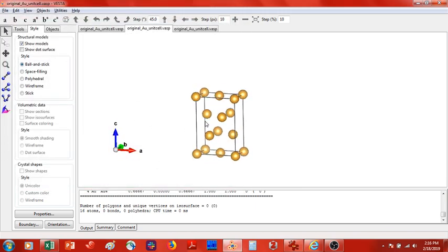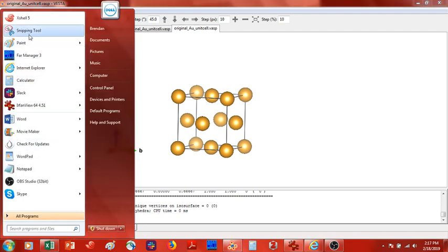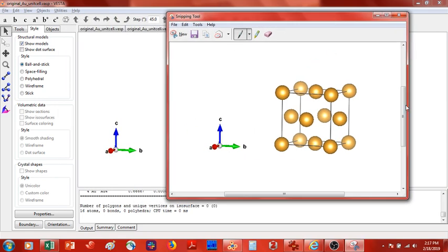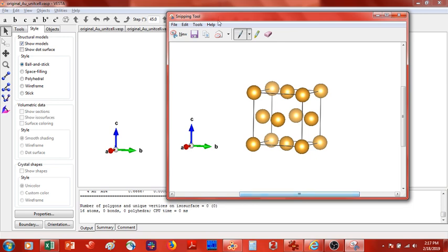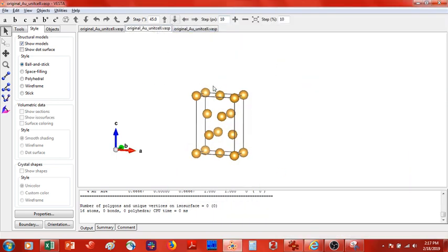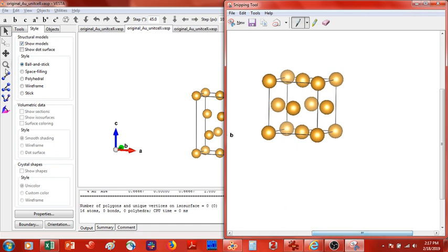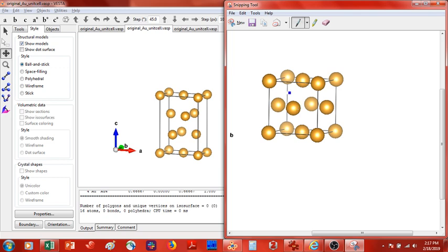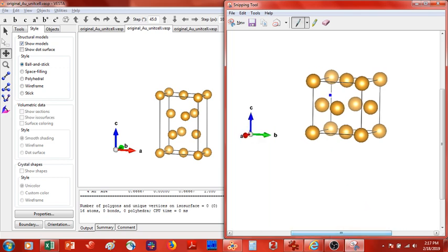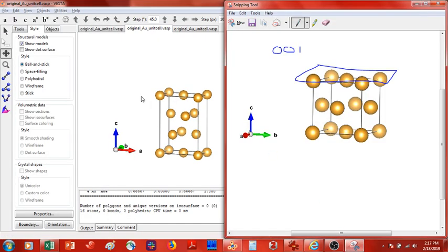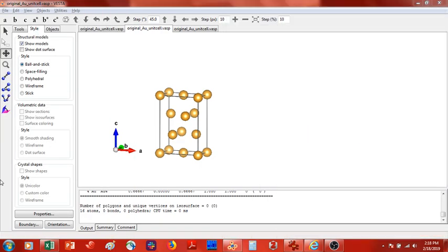As you can see here, this unit cell is a lot different from our original unit cell. Let me just take a snippet of this unit cell. You can see that this unit cell is very much different from the new unit cell. How is it different? It's different because in the original unit cell, this plane here, this was the 001 Miller indices. In this, this plane up here where I have in the C dimension is the 111 plane. Now what I would do is I could expand this unit cell here and place an adsorbate or molecule on top of it. Now I would be able to perform subsequent electronic structure calculations of molecules on the 111 face of gold. You can see that this unit cell is the same as the one we cut here.